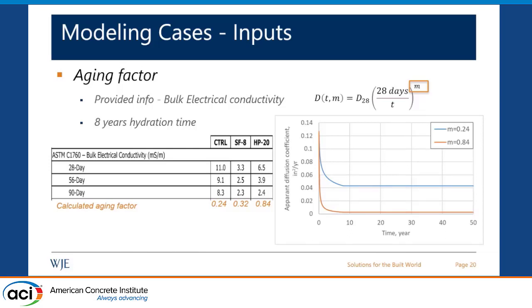And to give you an indication of how aging factor can affect the results, here are 2 curves, same D28, but with different aging factor. The blue line is using an aging factor of 0.24, assuming a hydration time of 8 years. So you can see you're getting to a value of about 0.04 with a lower aging factor. With a higher aging factor of 0.84, similar to what we are getting for the pozzolan mix here, you're getting a very, very low value at 8 years. You're getting down to 0.002. So aging factor affects the results significantly. And so it's very important to take a step back and evaluate the lab test results before using them in your model.